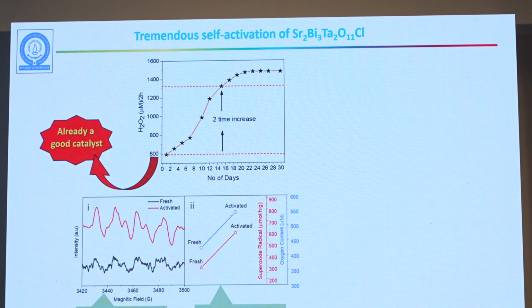Okay, and we looked at the mechanism very briefly. The mechanisms say that we have oxygen vacancies, where oxygen gets pinned, and more oxygen gets converted to O2 minus. You see, when a photocatalyst takes light, it produces excited electrons. This excited electron gets converted to oxygen. It forms O2 minus, and this is a signal for O2 minus. You see, this is for a fresh catalyst, and this is for the activated catalyst. So it produces more O2 minus, O2 dot minus radicals.